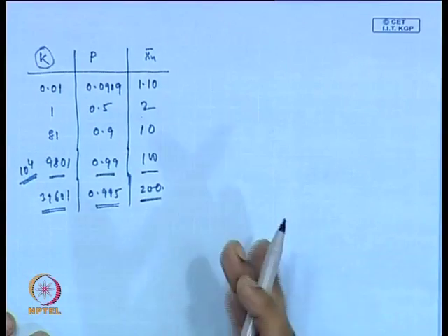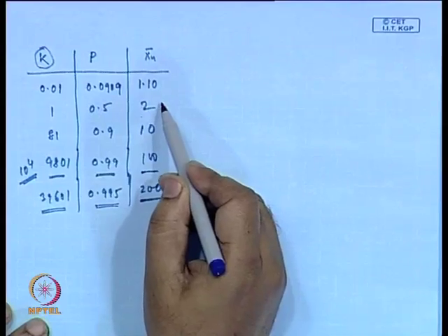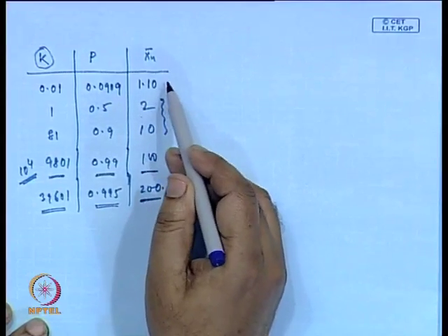Normally, typically polyesterifications are of the order of 0.1 to 10, polyamidation, which is probably the highest among the known common reactions, is about 10 to the power 2, and transesterification reaction is of the order of 1 to 10. That means, typically they hang around between these values.